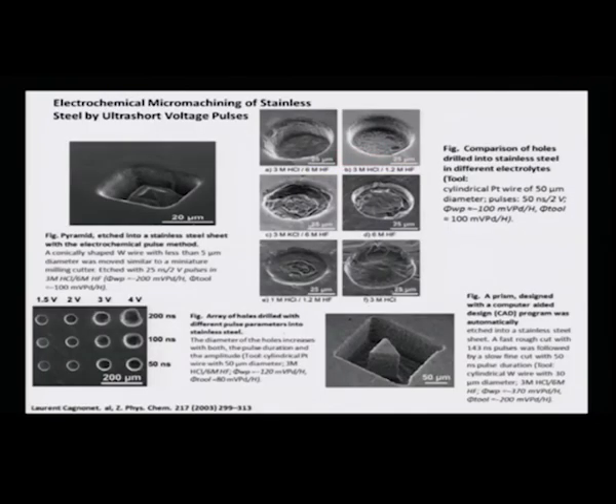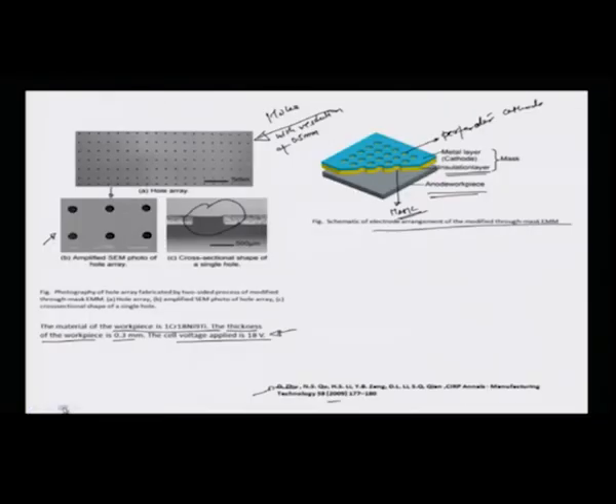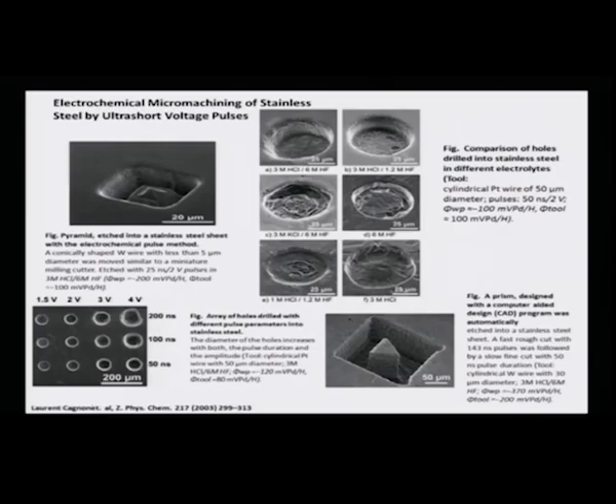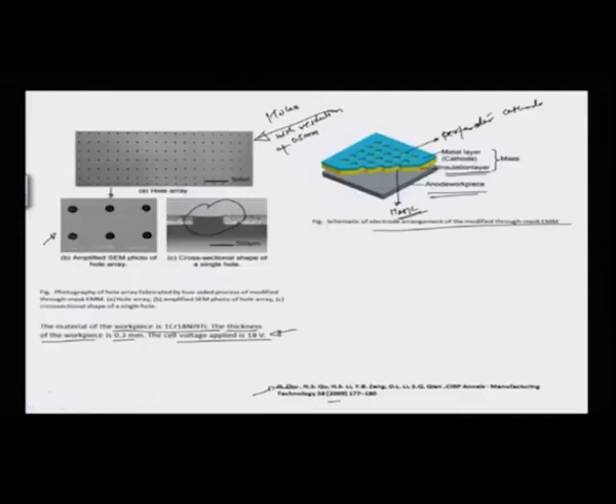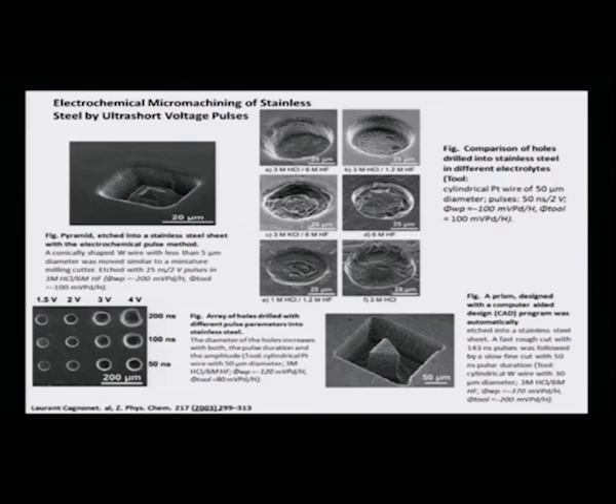So this gives you some feeling of the kind of voltages, resolutions and hole diameters that you can achieve with different workpieces. Yet another example is borrowed from the Cagnonet group, as can be seen in this illustration here. Okay. So this was reported in 2003, and this talks about, again, electrochemical micromachining of stainless steels by ultra short voltage pulses. The figure here is an SEM image of a pyramid which has been etched into a stainless steel sheet, again with the electrochemical pulse method. It's conically shaped. You can see the conical shape right about here in the center, and in this case a tungsten wire with less than 5 microns diameter was moved similar to a milling cutter. That's how the process was accomplished.